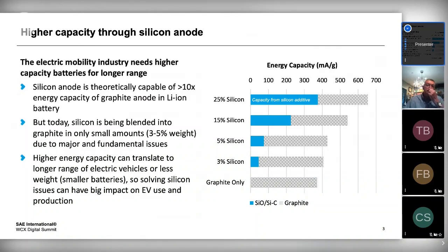Silicon is something that you can also push a much greater amount of lithium into. In fact, it can store 10 times the amount of energy over standard things today. However, at the moment, you can't use much silicon, and I'm going to explain why, and I'm going to talk about how graphene can help solve that. So, for a rough comparison, some numbers: the capacity of a graphite anode tops out at about 370 milliamp hours per gram. You could technically have over 3,500 milliamp hours per gram if you use silicon.